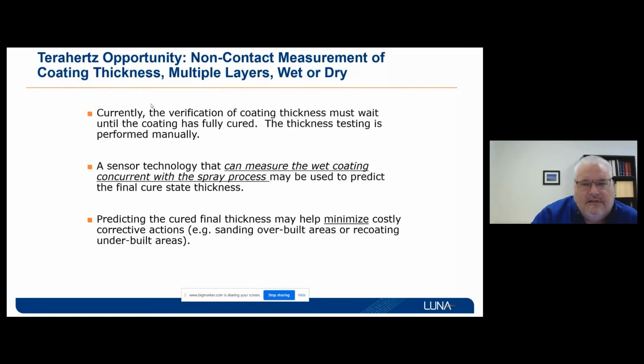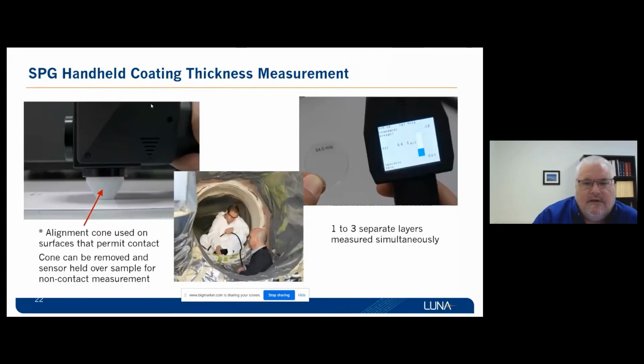In the case of, say, a spray robot application, verification has to wait until you've fully cured. This could actually take several days, 48 hours in some cases. The thickness testing is performed manually. So sensor technologies that can measure wet coatings or curing coatings can be used to predict the final cure state thickness and minimize corrective actions such as sanding overbuilt areas or recoating underbuilt areas.